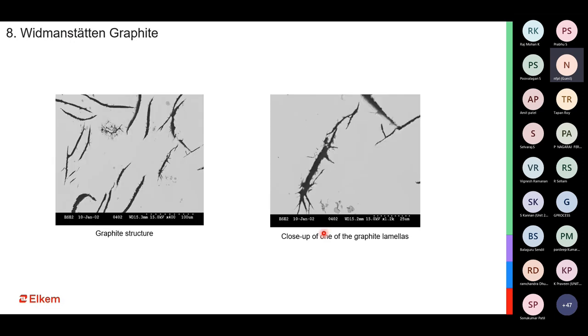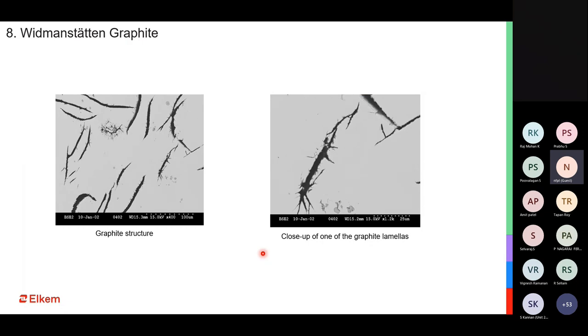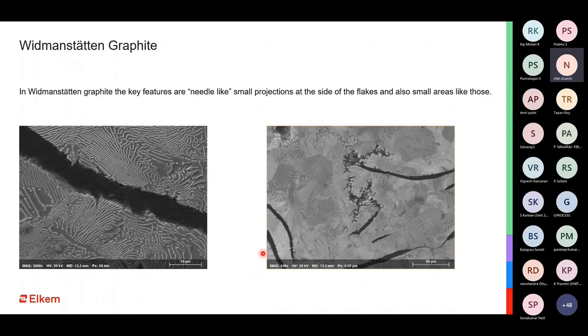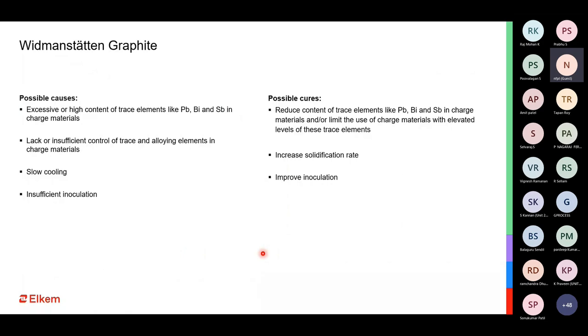Widmanstätten, a very unique kind of condition where the graphite flakes have a spiky, net-like structure around them. It is not able to hold its smooth or linear graphite flake shape. This happens mostly because of the presence of lead or bismuth or antimony in the casting, and where does it come from? It mostly comes in from your charged materials, because there is usually no other source for these elements to come in. How do you resolve it? The single and foremost way to resolve it is by having control on these trace elements in the casting.